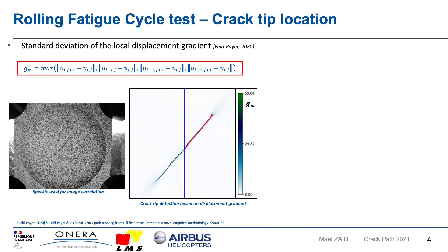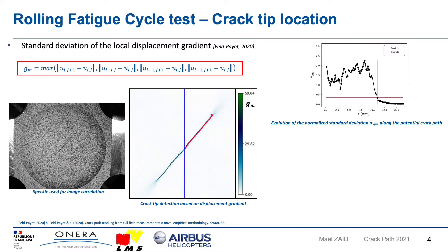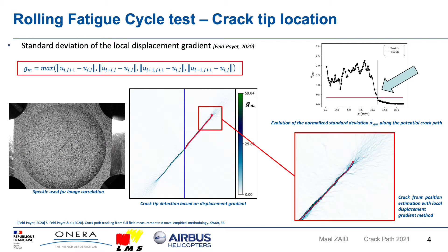In order to determine the crack growth rate, we must first estimate the position of the crack tip. To deduce this position from the measured displacement field, Feld-Payet proposes to position the crack by calculating the displacement gradient of each pixel from the digital image correlation. A crack tracking algorithm is applied to follow the evolution of the displacement gradient until a progressive decrease, which is considered to be the crack tip. These results were compared with those from direct optical observations and a good agreement on the crack tip location was observed.